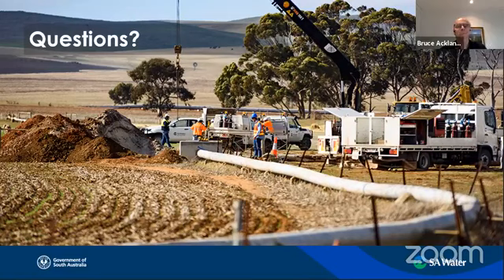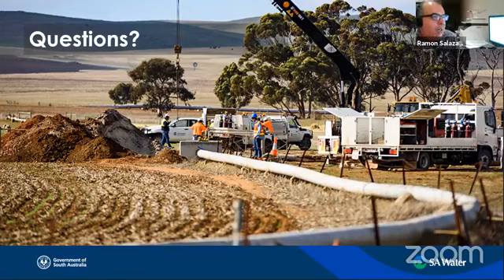She asked, "Why don't you use the bentonite bag?" Well, actually, we're using this Borium Stealth 2 reference electrode, and I just read that they say no, don't use a bentonite bag, so use the native soil. Apparently the plug retains, or is supposed to retain, moisture, so they don't recommend using the bentonite bag. So basically the contractor just followed the instructions, and I'm just wondering if that could be a problem, or maybe we're doing a wrong installation.